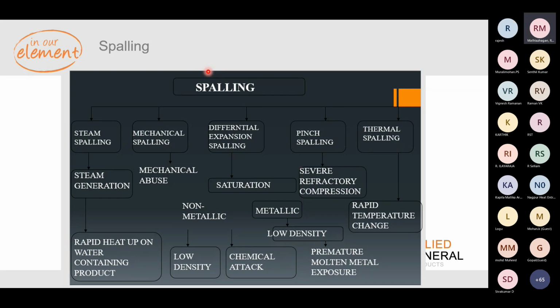So it can be because of metallic and non-metallic. And as I said, it can be because of low density and chemical attack. So make sure you properly sinter the furnace, properly line the furnace, and this can avoid saturation. Pinch spalling is again because of refractory compression.